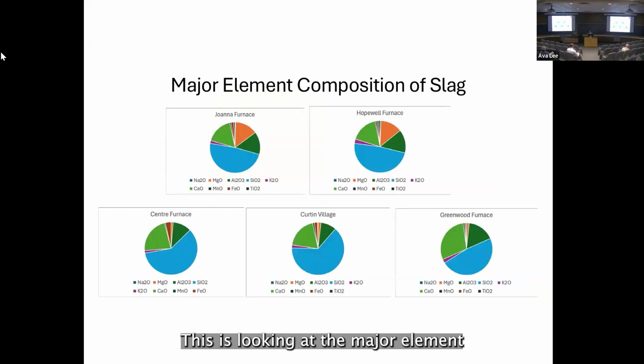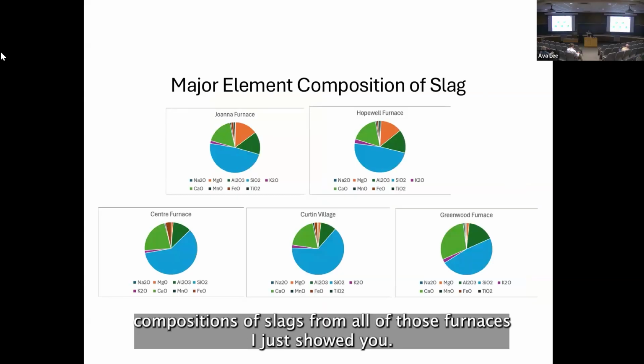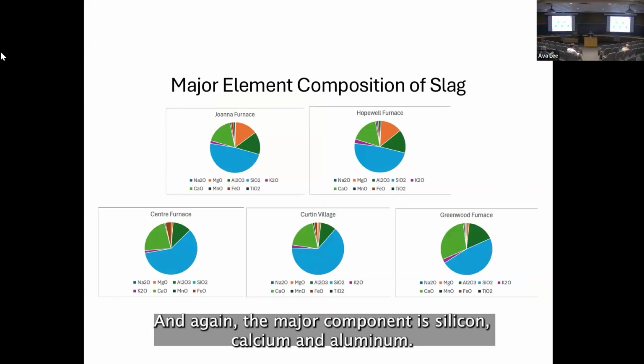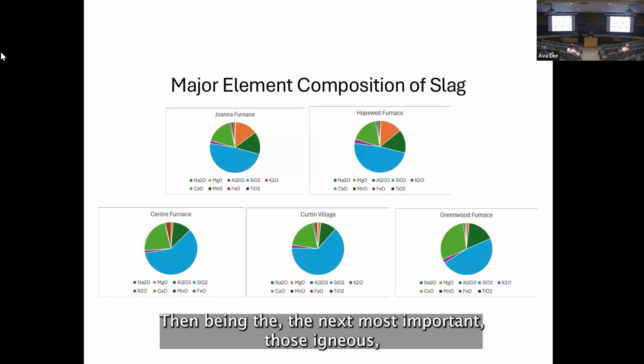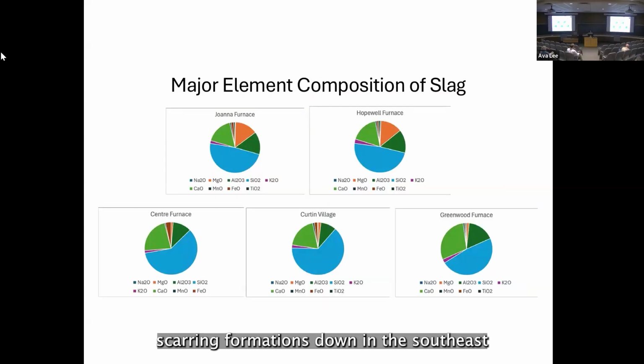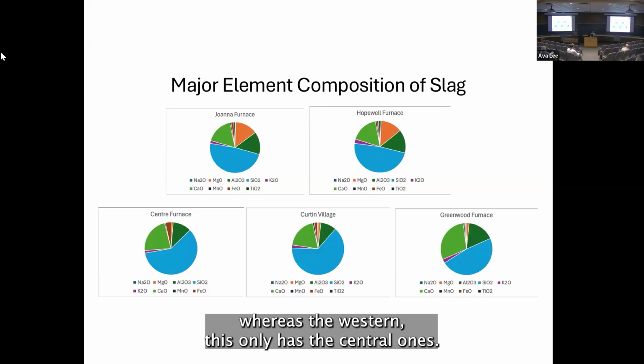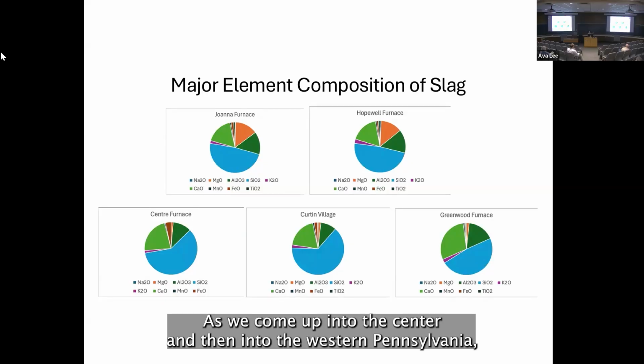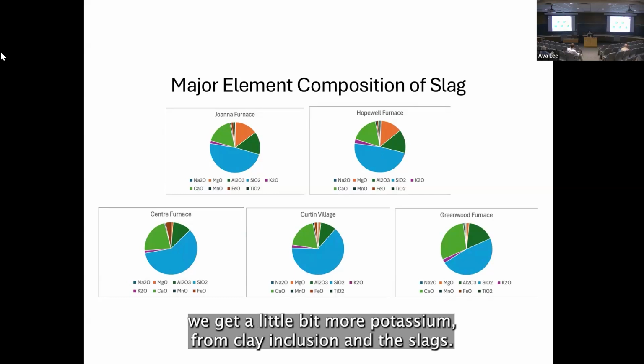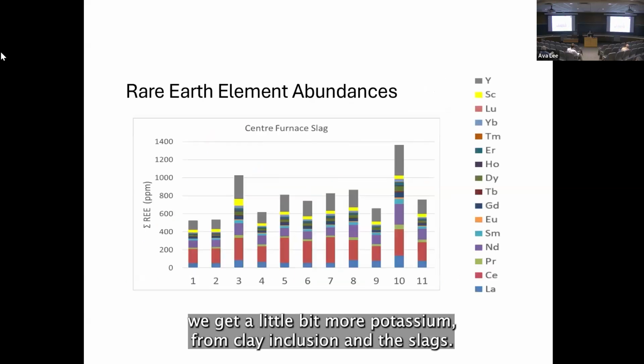This is looking at the major element compositions of slags from all of those furnaces I just showed you. Again, the major component is silicon, with calcium and aluminum being the next most important. Those igneous skarn formations down in the southeast corner produced magnesium-rich slags. As we come up into the center and then into western Pennsylvania, we get a little more potassium from clay inclusion in the slags.